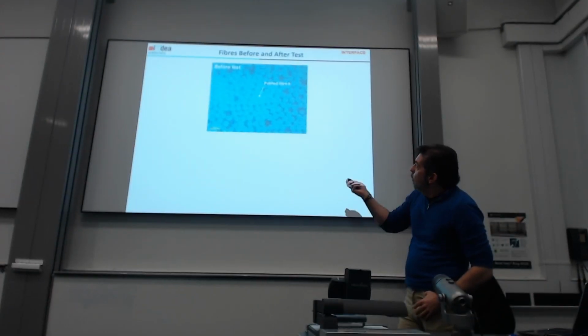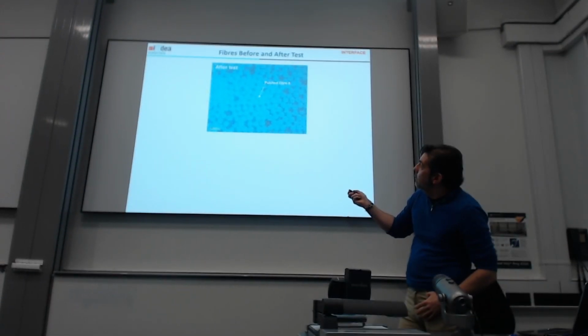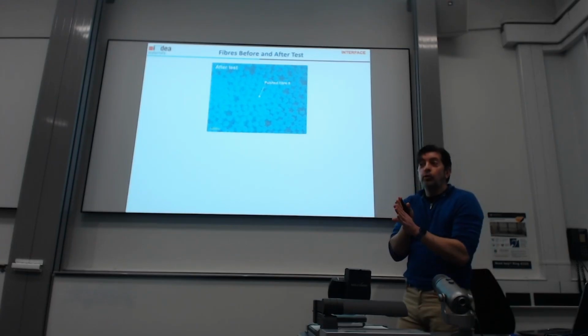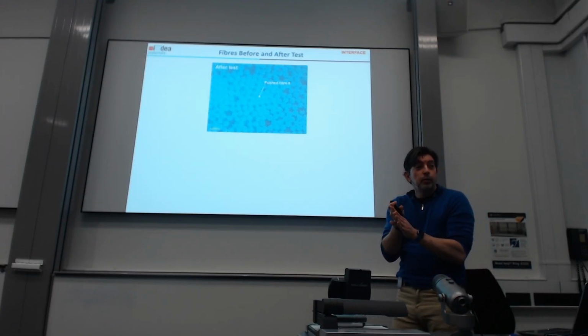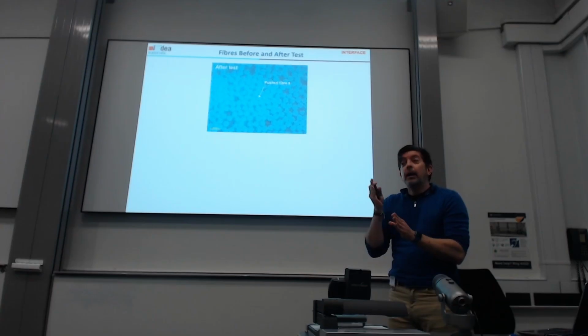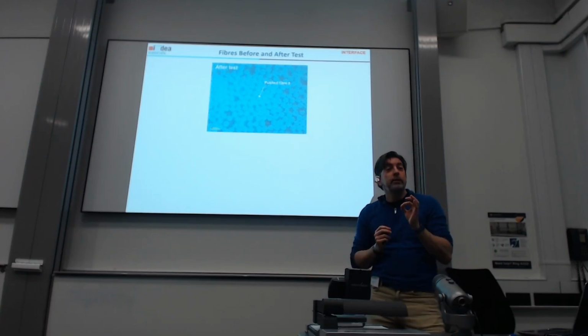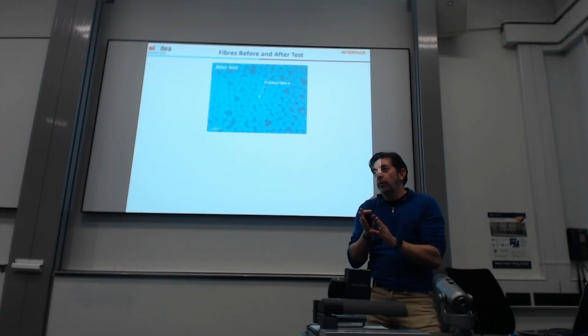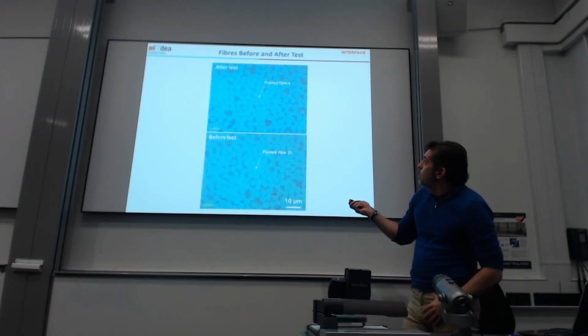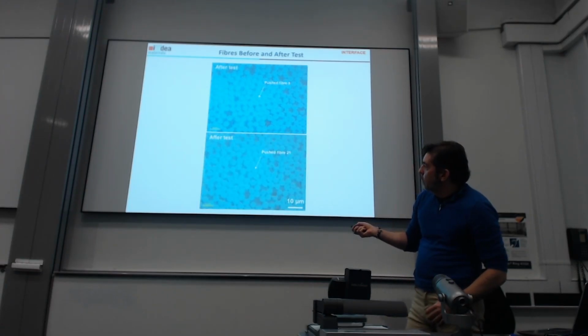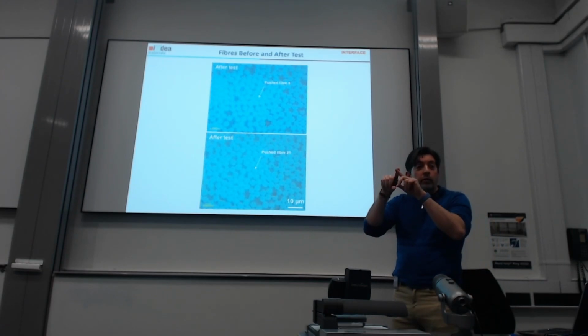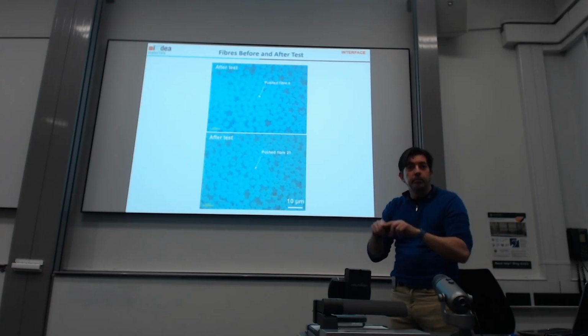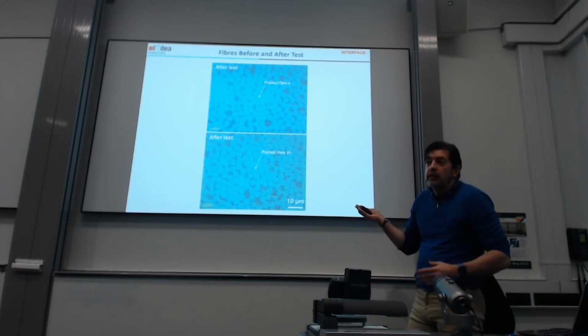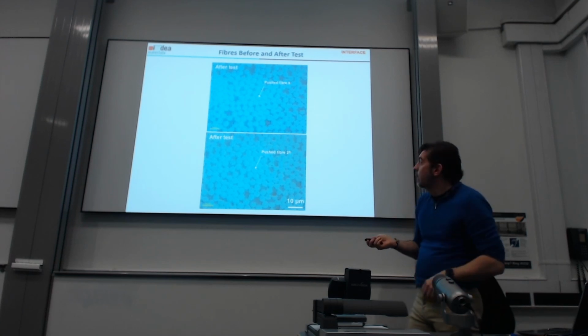So this, for example, is a pushed-in fiber, and you can see before and after the pushing. I like to have an image before and after to make sure I'm pushing on the right one. The test has good accuracy, so once you have a good calibration, obviously, you can push. And this is another example on a wet sample. You can see a clearly debonded region around the fiber. So I would consider that a successful test.